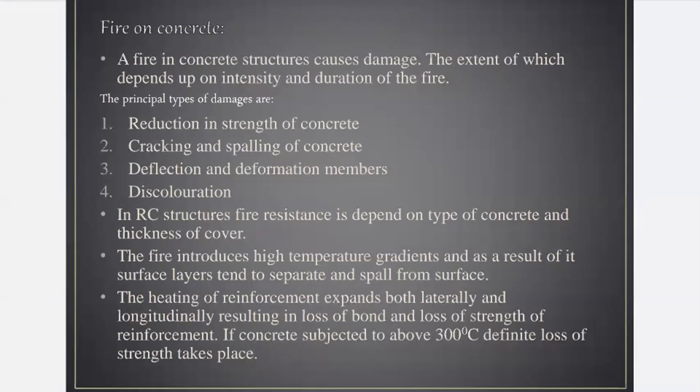As per IS 456:2000, you should provide minimum cover of 30 mm for beam, 15 mm for slab, 40 mm for column, and 50 mm for footing. Why is this so? Because if fire is on your concrete, it cannot directly reach the reinforcement zone. If the fire reaches the reinforcement zone, there will be a loss of not only compressive strength but also tensile strength, which leads to big cracking and big deterioration of your concrete.